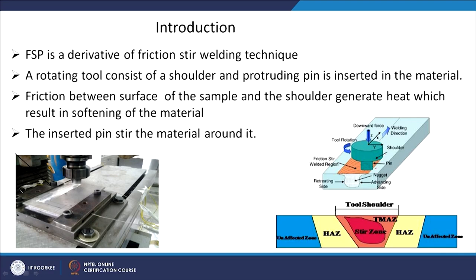This tool is now rotating at a good RPM. The shoulder will rub against the surface of the workpiece and generate heat through friction. This heat will dissipate around, and at higher temperature we have already seen that the flow stress of the material keeps coming down — basically materials become soft. Then this rotating pin stirs the material around it, so this soft material will be continuously stirred around the pin.